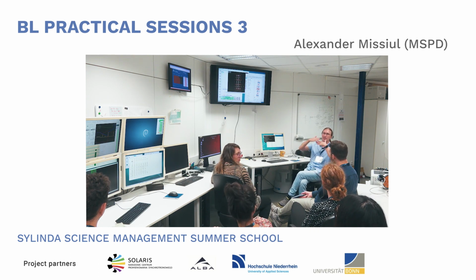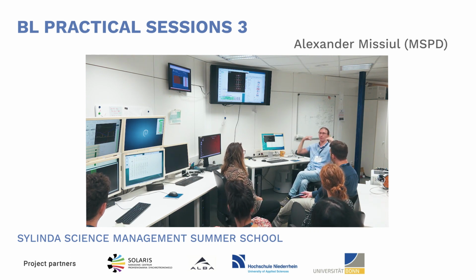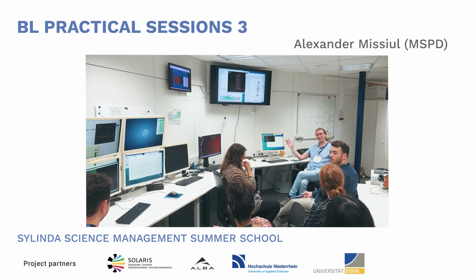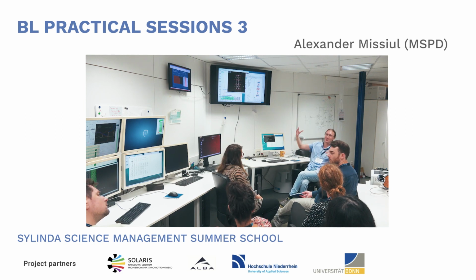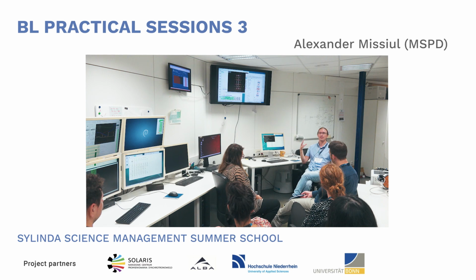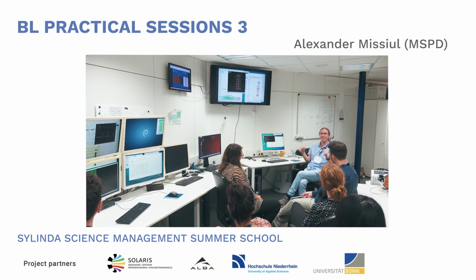Okay. Again, there will be several levels of analysis, starting from very qualitative analysis, just to say, here we have these interatomic distances. It changes somehow depending on the conditions. For example, it's very typical for cements. Normally they have lots of amorphous phase, and they just look at whether some peak moves, and they make some conclusions from this. Or you can really try to model your material, which is much more complex. But the software exists. It's not so easy to use, but it's possible.